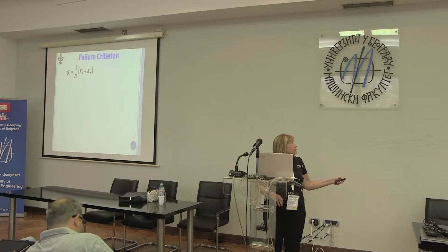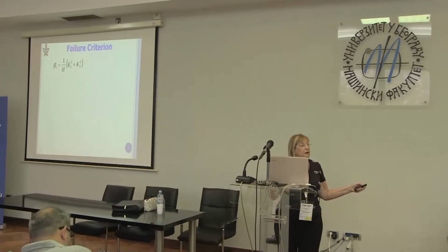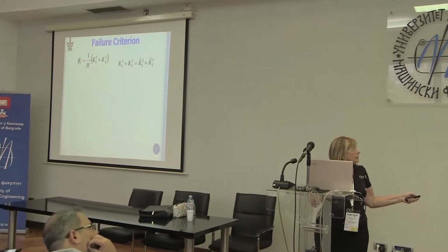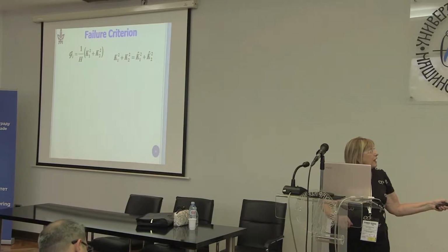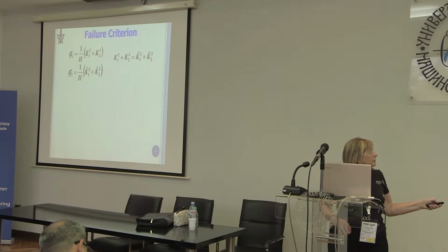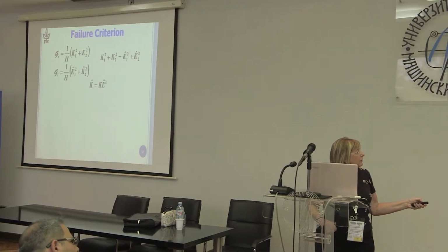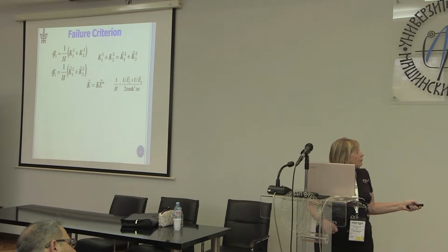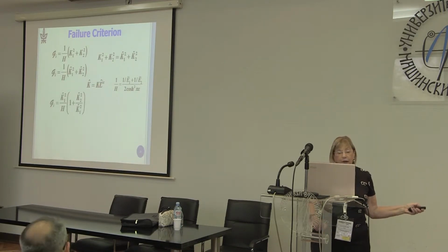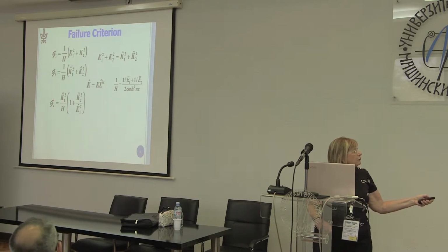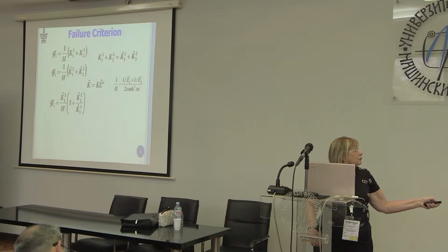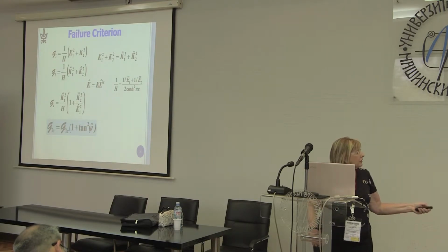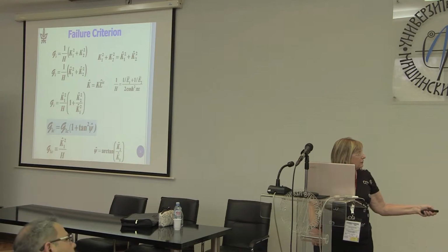So we start off with the interface energy release rate. We're only looking right now at an in-plane problem, and we know that K1 squared plus K2 squared are equal to the hat quantities, the normalized quantities without the epsilon in them, and so we can rewrite G. I remind you the relationship between K and K hat in terms of L hat, and I remind you the expression for H, and if you factor out K1 squared, you have a coefficient, and you have 1 plus K2 squared over K1 squared, which is none other than psi hat, K2 hat over K1 hat.